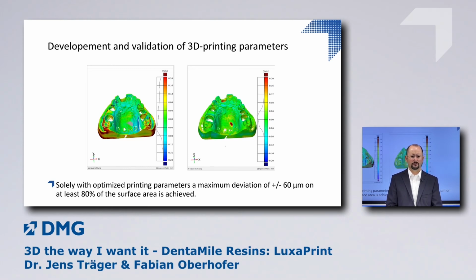And for example, for a model, we want to have a deviation not exceeding 60 microns on at least 80% of the surface. And you can see an example which we of course would not give out into the market, but just to show what could happen if this has not been done right in terms of parameter development. We have parts that are too big. There's too much material shown in red, and we have these bluish parts where there's not enough material, and we have a deformed object, also seen from the histogram here, which is not accurate in terms of the digital data set.